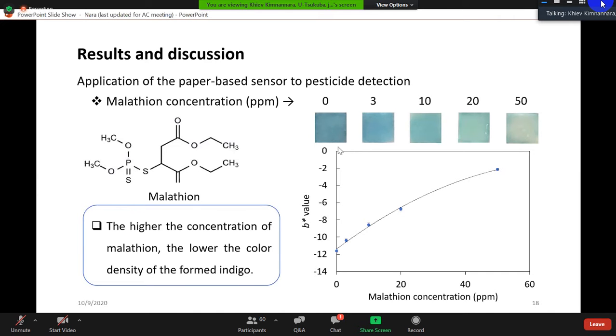Not only the color density based on the image, but based on the B value, you can see that the B value is increased when we increase the concentration of pesticide. For example, at 0 ppm, without a pesticide, the B value is just around minus 11.80, and it reached around minus 3 when we apply 50 ppm of pesticide. So it means that the higher the concentration of malathion, the lower the color density of the indigo formed.